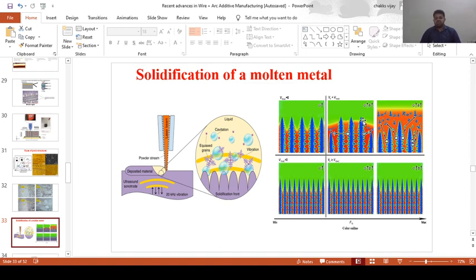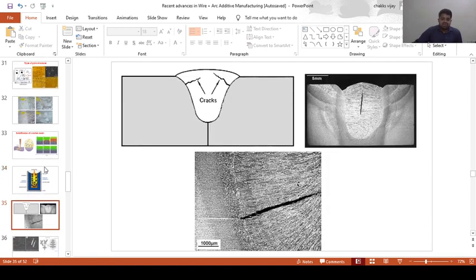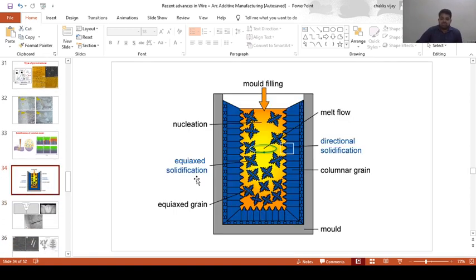Wherever the heat dissipation rates are very high, in that particular direction your grain will try to grow. So it's up to you in what direction you are planning your grain to be grown. In that direction, you have to cool your sample very rapidly, so that in the fastest heat dissipation direction, these grains will try to grow. That's one of the most important things I would like to touch upon.